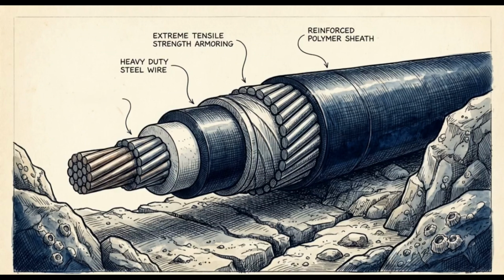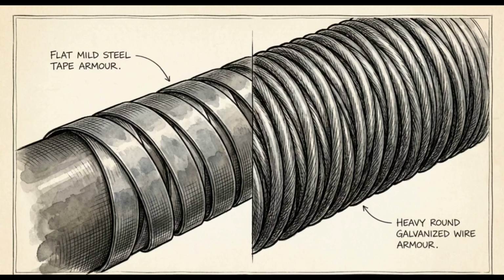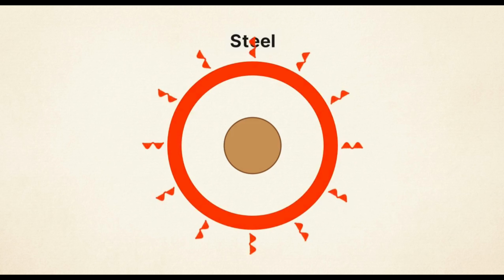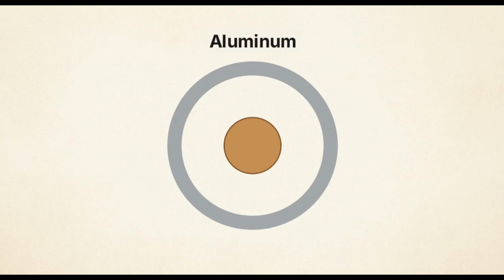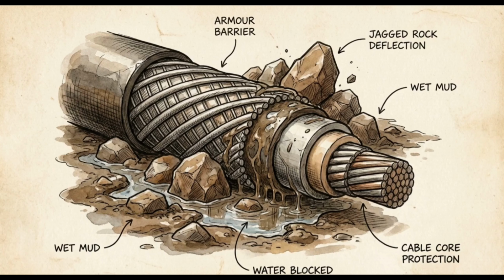If the installation environment requires higher tensile strength, such as in submarine cables or solid-type lines carrying over 11 kilovolts, engineers swap the flat tape for tightly wound galvanized steel wire. Alternating current induces a fluctuating magnetic field. Wrapping that field in steel creates inductive resistance, causing the armor to rapidly heat up. Swapping the magnetic steel for non-magnetic aluminum wire drops the inductive heating effect to zero. The exterior layer must block the physical environment from getting in, while simultaneously protecting the entire cable system from the violent magnetic fields generated by its own internal core.